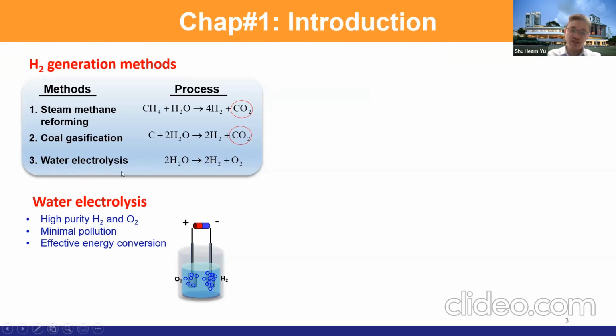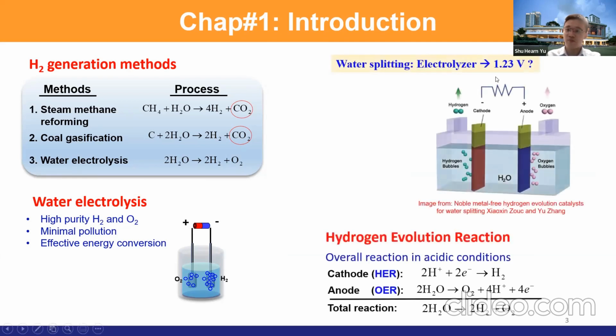So water electrolysis is a very promising method because we can split the water electrochemically at room temperature at about 1.23 volts and above. Basically, we can apply a positive potential and a negative potential across a cell, and it will generate oxygen and hydrogen. The advantage of water electrolysis is that we can generate high purity hydrogen and oxygen. There's minimal pollution because no carbon dioxide is generated as a byproduct, and the hydrogen is readily converted into electricity with a fuel cell.